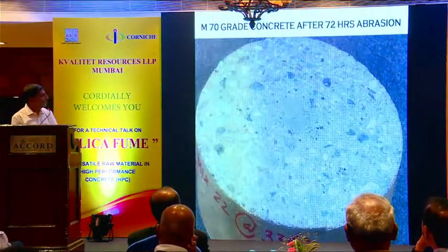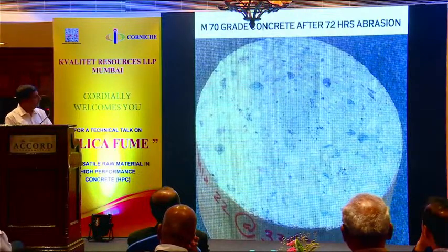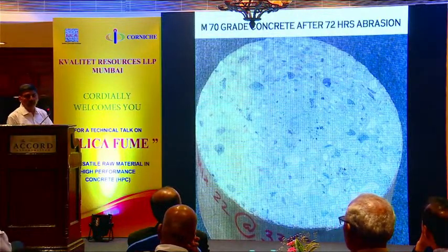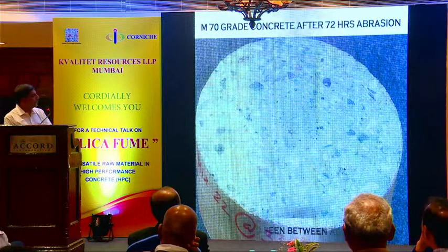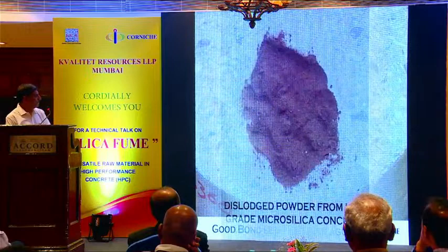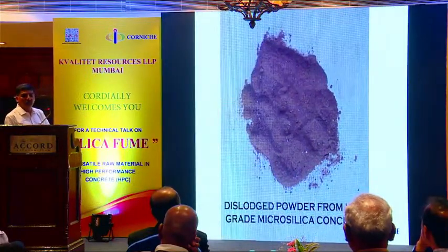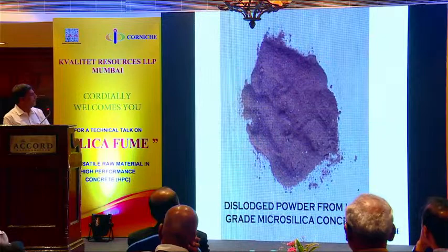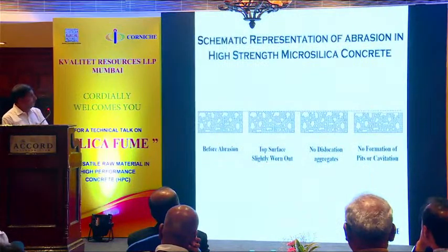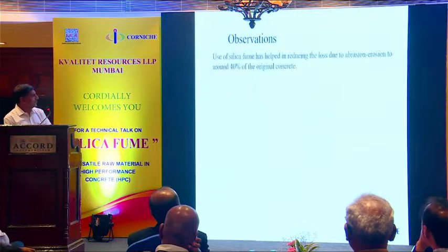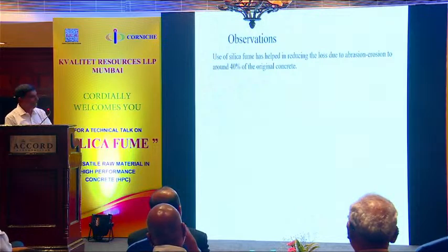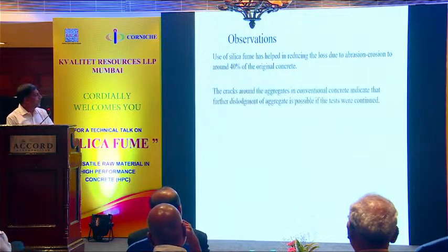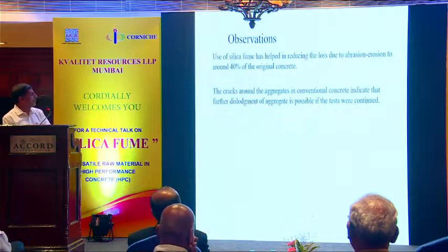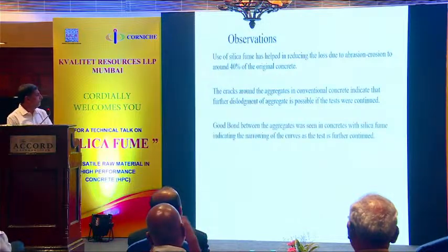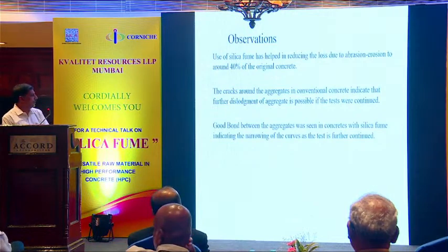With silica fume, M70, after 72 hours, only the top watery layer had gone off. The bond looks good. Have a look. And the residue, no peeling of aggregates or anything. They were holding on. So observations: use of silica fume concrete helped in reducing the loss on abrasion by around 40%. The cracks around the aggregates in conventional concrete indicate further dislodgement of aggregates if tests were continued. A good bond between aggregates was seen with the silica fume concrete.